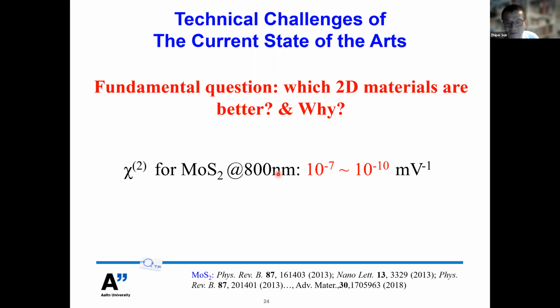The reported Chi2 can have a three-order-of-magnitude difference if you compare the results from different groups. The difference is quite understandable because different groups use different lasers with different pulse durations, different focus conditions, and even different calculation equations. So this makes the comparison of 2D materials very complicated.